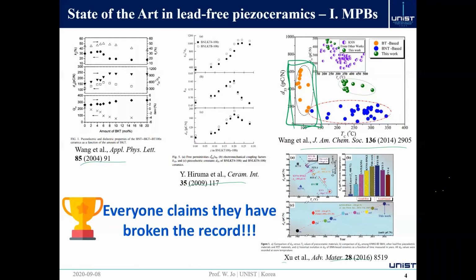But these days I'm devoting myself largely to real-time applications. What I realize is that Curie temperature is really important, even though people usually sacrifice Curie temperature to get a better piezoelectric coefficient. The reason is quite simple. A piezoelectric element cannot stand alone for device applications. It has to be attached somewhere, and for that, you usually use epoxy, the glue. The typically available glue has a glass transition temperature of more than 100 degrees C. That means if the Curie temperature is less than 100 degrees C, the material cannot be used for those applications.